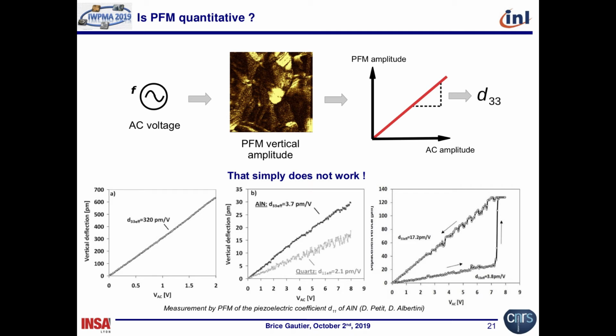Here, this is quartz. So we measure the quartz. We find 2.1 picometers per volt. Well, the real value in the books is 2.3. Okay, we can be confident with this value, 3.7. Well, it should not be so far from the real value of the piezoelectric coefficient. The problem is that it's not reproducible, so you can't rely on it.